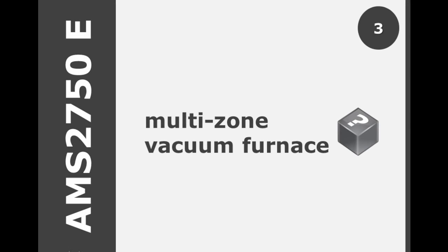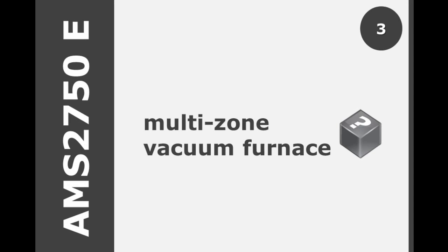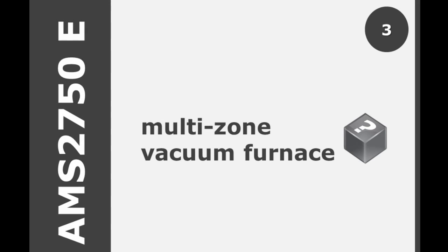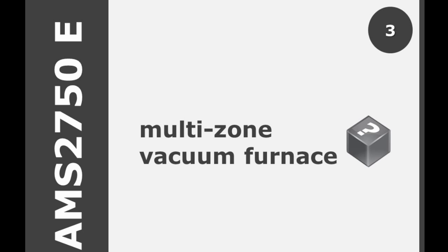In E, rather than applying this to each control zone, you can split the entire working volume into 20 cubic foot zones and treat each of these zones as a single control zone to determine the overall number of high, low, and load sensors.